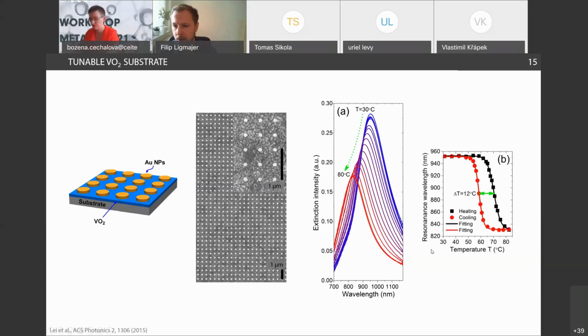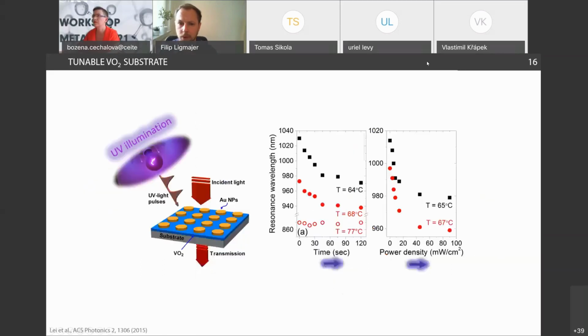Here is a plot showing the resonance wavelength extracted from these experimental data as a function of temperature. And here you see the typical hysteresis that is characteristic for many phase change materials actually, or for other phase changes, not only the structural ones, where you see that you need to decrease the temperature slightly more in order to get VO2 back to its original state. And the width of this hysteresis tells you something about the quality of your film and about mono or polycrystallinity of your VO2.